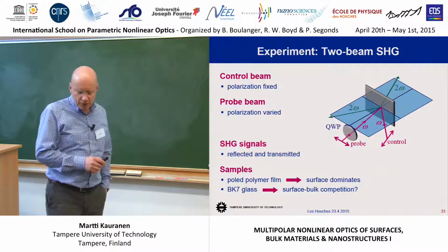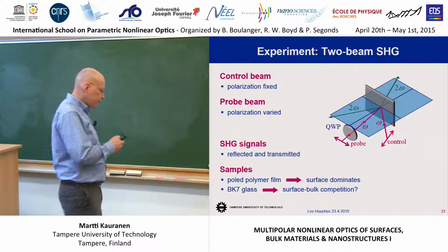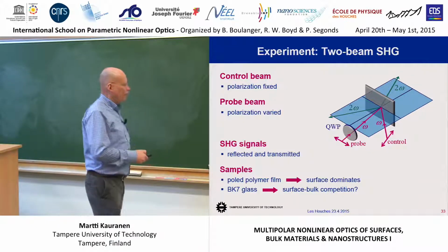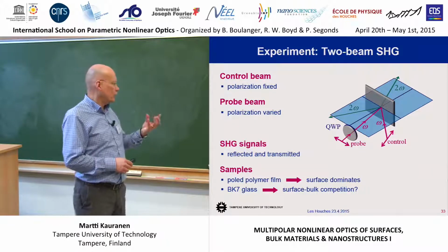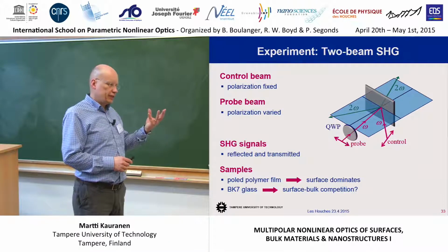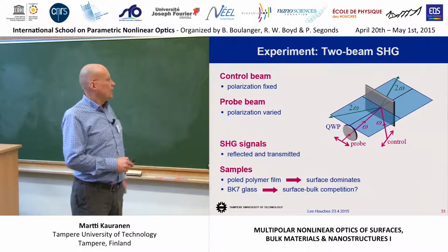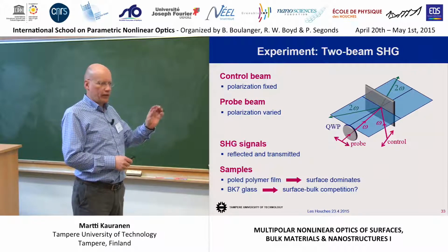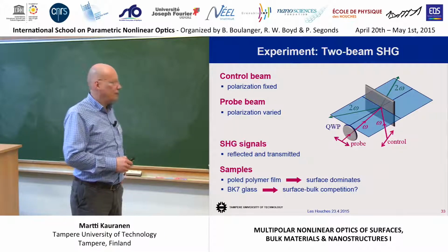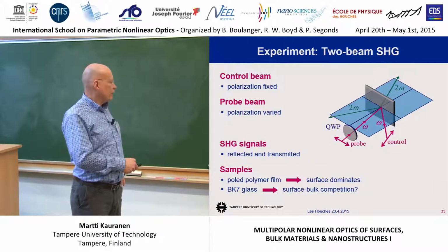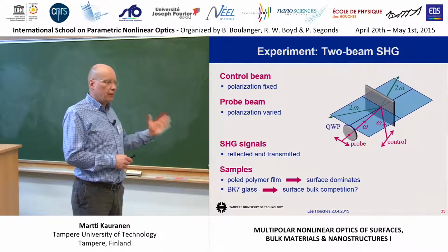And we used two different types of samples. A poled polymer film, which is supposed to have a really strong surface-type response, and a film which is much thinner than a wavelength, so we don't have to worry about phase matching. And then just a BK7 glass. And we were hoping that we get some type of interferential competition between the surface response and the bulk response.